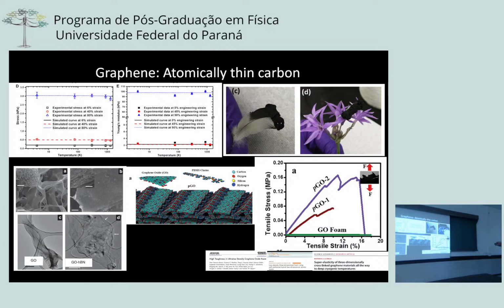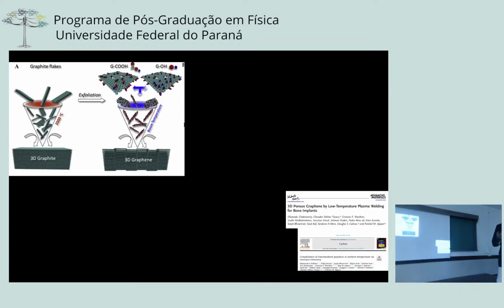And subsequently we keep on doing it, and that is where Cristiano and I worked together. What we have done in this work is we take this porous structure, put a small amount of polymer, and the polymer just comes on the edge and gets them connected. If you connect them, a foam which is good in compression gets good tensile strength as well. And that's what we observe in experiment, that you can have a good tensile strength in foam as well by just putting a small amount of polymer which will get connected on the edge. Also you get a lot of advantage in processing material.